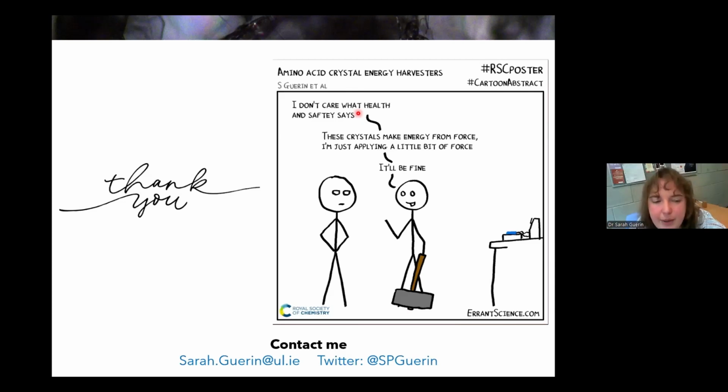Hmm. Yeah, that's a great question. I mean, piezoelectricity is a bulk single crystal property. So in theory, no matter how you obtain your crystal, the properties should always be the same at the single crystal level. Unless there are some very cool studies that have literally come out in the past couple of months that have looked at crystallizing in magnetic fields, crystallizing in electric fields, that definitely for polycrystalline samples creates that orientation. It's the equivalent of poling, what we do with ceramics, to do that. But no, in theory, no matter how your crystal is made, you should get the same properties every time.